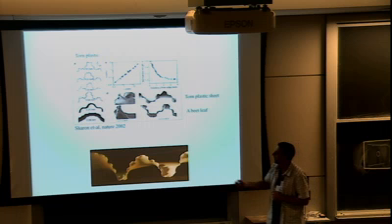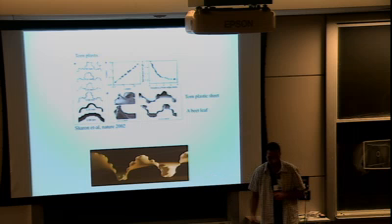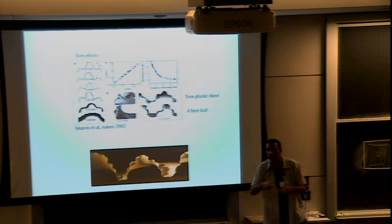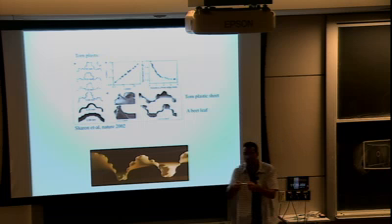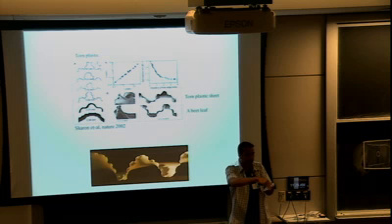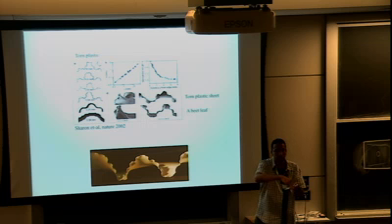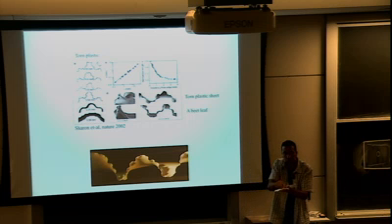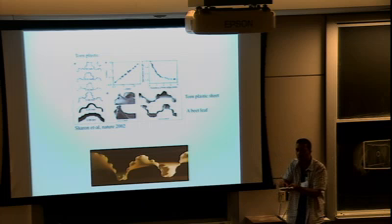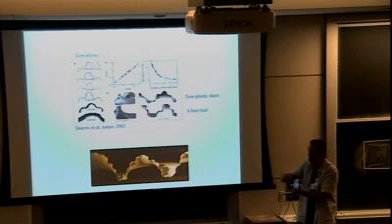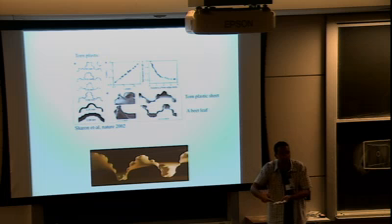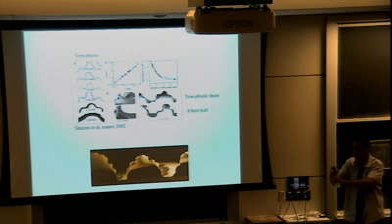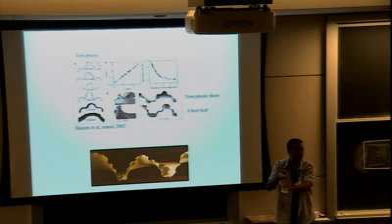And we can show that everything you could see here actually comes from a 2D input. All we do is differentially elongate this plastic sheet away from the boundary. Pieces that are very close to the torn edge are stretched tangentially a lot, and then this tangential tension diminishes as we go into the bulk and goes down to 0. This induces a hyperbolic metric, a metric of negative Gaussian curvature. And we saw that when it is embedded, it gives rise to saddle-shaped objects.